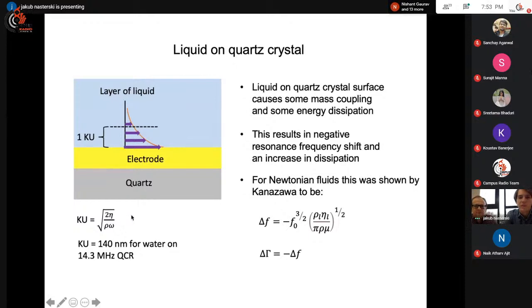And for a 14.3 megahertz quartz crystal with water, this distance is only 140 nanometers. So when you go farther away from the surface, the water is not affected. And how the vibration parameters are affected is that the resonance frequency decreases because there is some mass coupling of the water